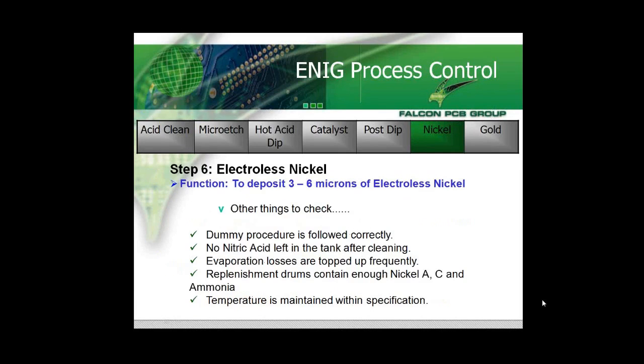And what we're looking to try and do is, the first thing that you tend to see as a problem is the electroless nickel will start plating out onto the floor and the sides of the actual bath walls. Then, of course, we have to pump out very quickly, and we have to use a hot nitric acid to dissolve that plated out nickel. It's absolutely essential that when we've done this that we don't damage the tanks, and we don't leave any traces of the nitric acid left in the tank, or the new solution, of course, would not work very well.